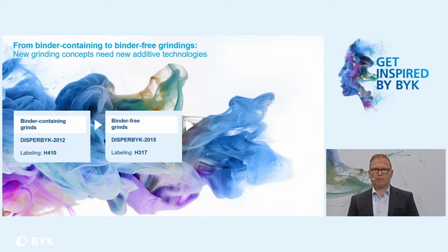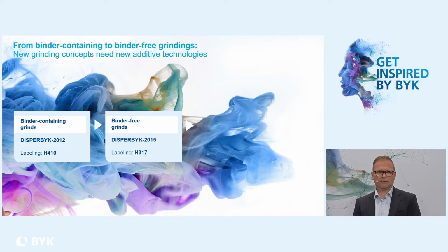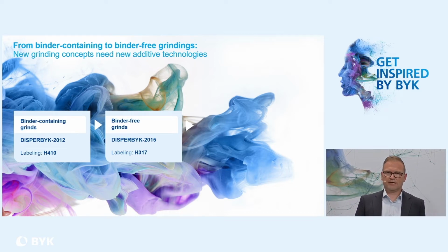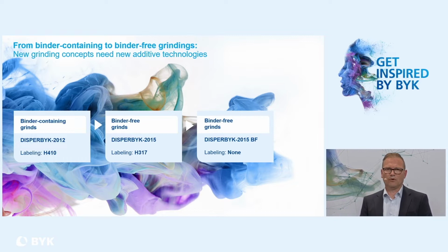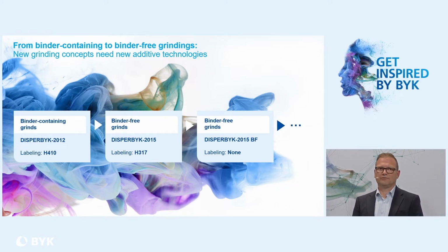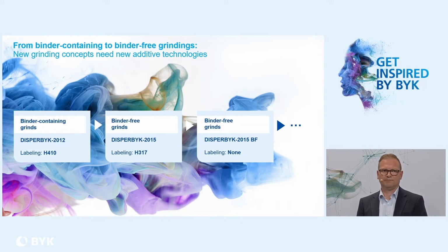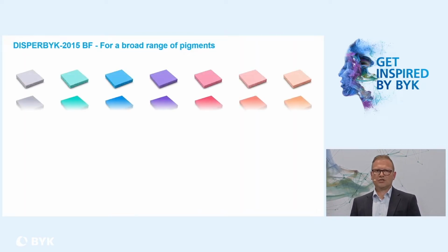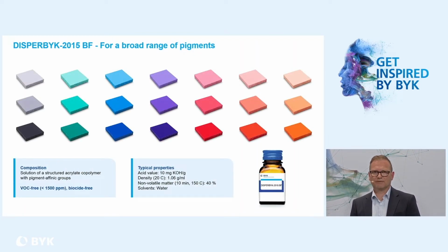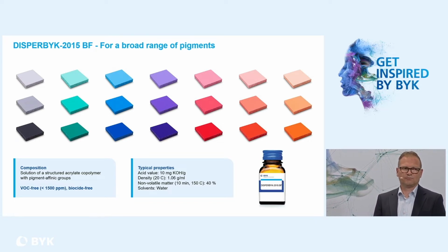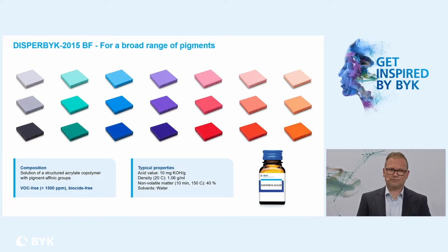The pigment concentrates with our binder show a broader compatibility to different systems. But you see also here on this slide again already, this BYK 2015. Labeling H317 comes from the biocide package in the additive. And therefore, the further development was this BYK 2015 BF. BF stands very simple for biocide free. So now, a wetting and dispersing additive, labeling free, especially for a broad range of organic pigments, and especially for wood coating formulations. It is a solution of a structured acrylate copolymer with pigment affinic groups. It's VOC-free and, as mentioned, biocide-free.